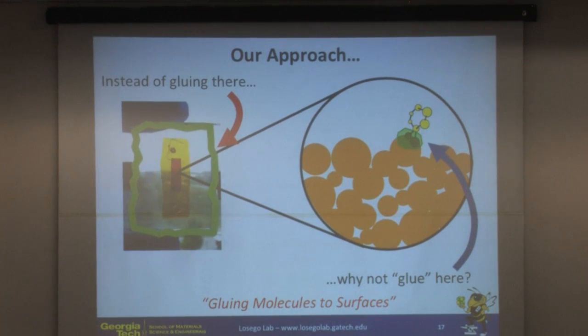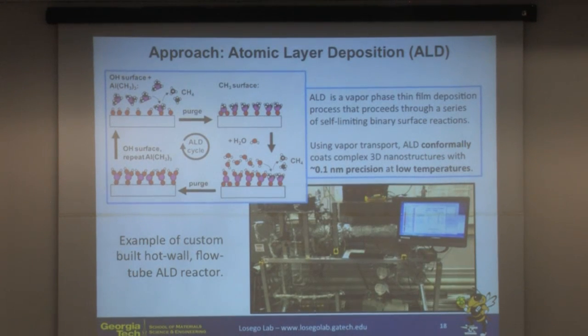Okay, so our approach has been, instead of gluing on the exterior, what if we were able to glue the molecule right at the site of attachment? And that's really been the revolution that we've created, is attaching the molecules right at the surface. And so our approach, again, has been using these vapor phase deposition techniques, atomic layer deposition. So we've gone over the process. This is one of the reactors in our system.